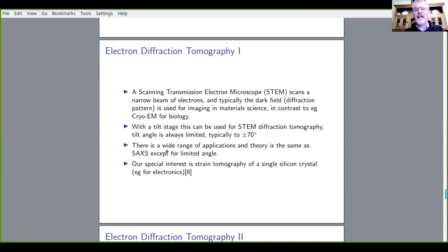Electron tomography has 2 flavors, actually. One is the cryo-EM that you see in biology. If you've tried to help out with the coronavirus imaging, typically they have a frozen sample, and they have a parallel beam electron tomography system with a limited tilt angle. So up to some details, it's parallel beam tomography with limited angle data. In practice, the sample degrades as you bombard it with electrons, and there are all kinds of other modeling problems, but it is essentially parallel beam tomography.